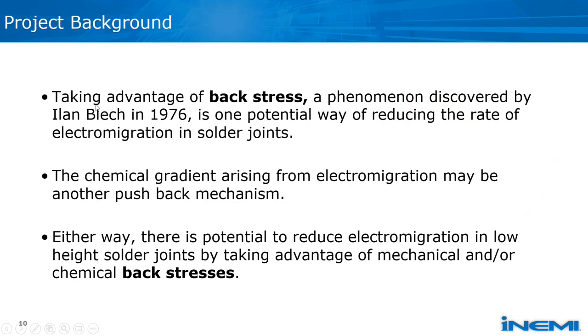So as I mentioned, we want to take advantage of back stress. This phenomenon was discovered by Ilan Blech, and this is a potential way of reducing the rate of electromigration in solder joints. I mentioned stress. There's also a chemical gradient, because bismuth is being pushed in one direction, so its concentration is increasing. So there is a chemical gradient, and that may also cause pushback. So there are two mechanisms that can cause this pushback.